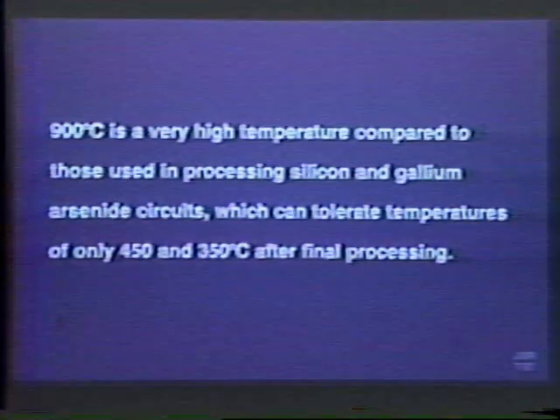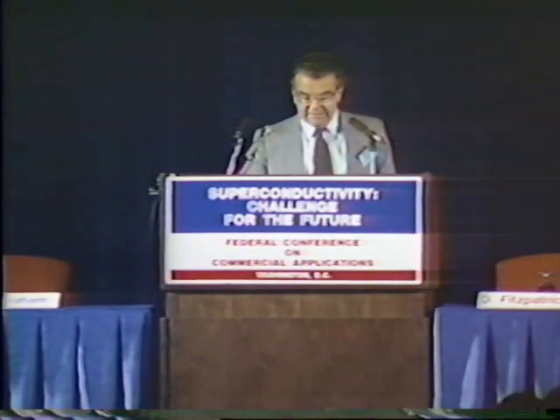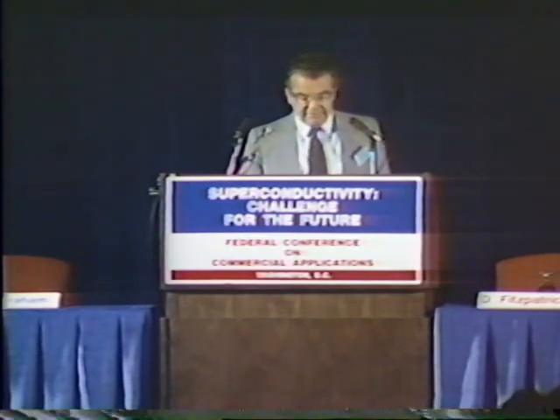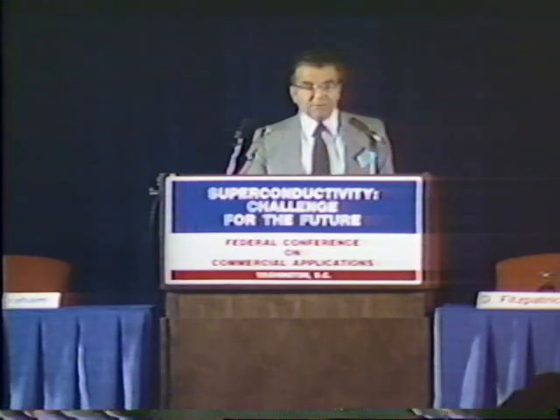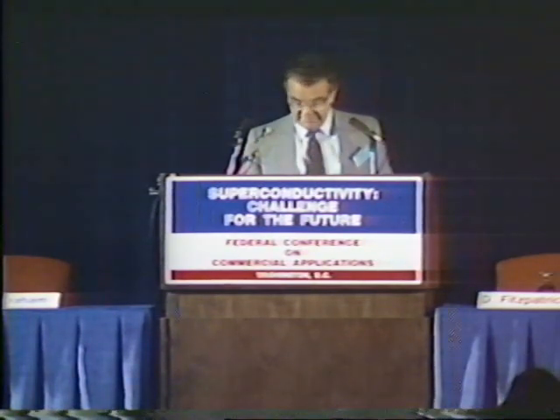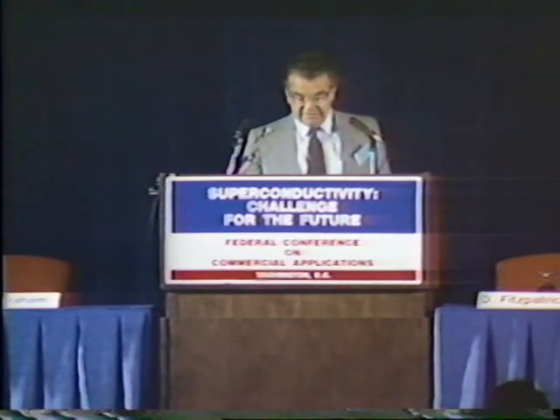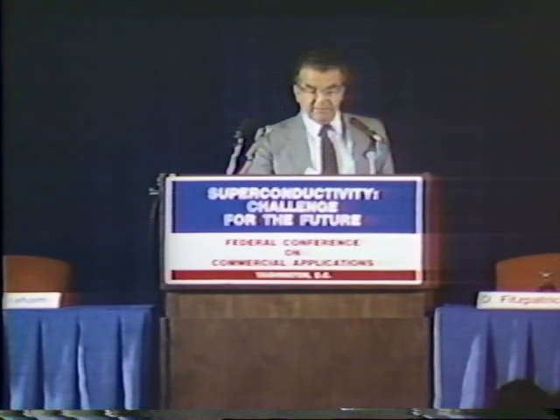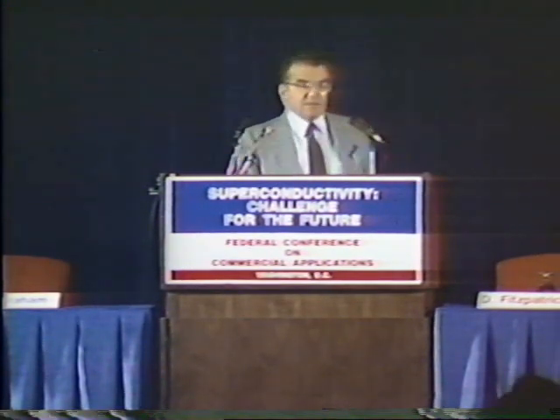So in the next slide, let me just state that 700 or 900 degrees, whichever turns out to be required, is a very high temperature compared to those used in processing silicon and gallium arsenide circuits. I mean, some of the steps are relatively high in that processing. But if we're thinking about hybrid technologies in which semiconductors and these superconductors are used together, then after the semiconductor devices are complete, they can only tolerate temperatures something like 450 or 350 degrees C in the case of silicon and gallium arsenide. Thus, you would assume, and I'll try and show you there are some complications with this, that superconductors in hybrid circuits must be applied before the semiconducting devices are processed. And this is kind of constraint number one in the way that you might work with these materials. The second problem is on the next view graph.